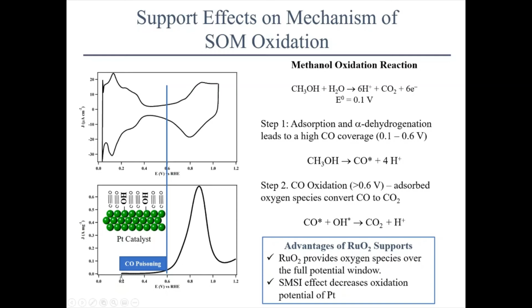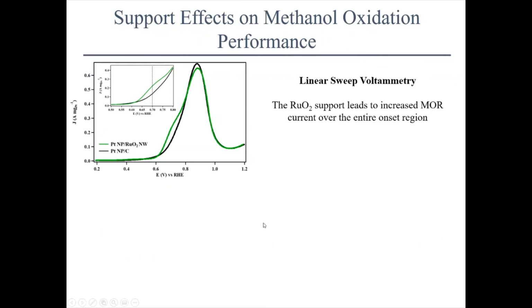Basically, this run up here is what we call overpotential, meaning excess potential that you would need beyond the thermodynamic potential. So when we compared the methanol oxidation from the ruthenium oxide support to the carbon support, we see that we get this bump in the activity, and we get much higher activity over the entire onset region. In essence, the ruthenium oxide contributes to a much larger MOR activity relative to the carbon support, especially at low overpotentials, which is important because the low overpotential region is what you would want for a fuel cell.